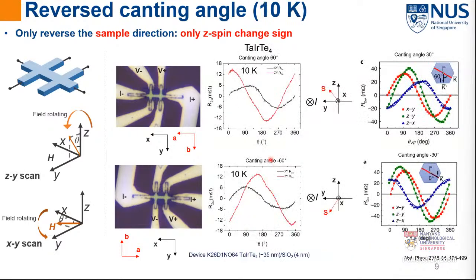So we performed the same experiment at 10 Kelvin, which shows a much larger canting angle. By changing the current flowing direction from A-axis to minus A-axis, it can be clearly seen from the figure that the canting angle has changed from the positive case to the negative case, which is 60 degrees along the A-axis and minus 60 degrees along the minus A-axis. This is similar to the published Nature Physics data, which shows a canting angle of 30 degrees and minus 30 degrees.